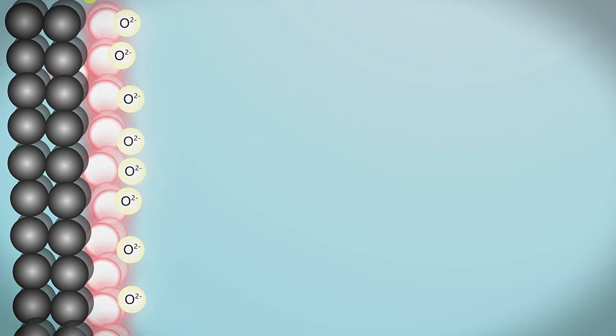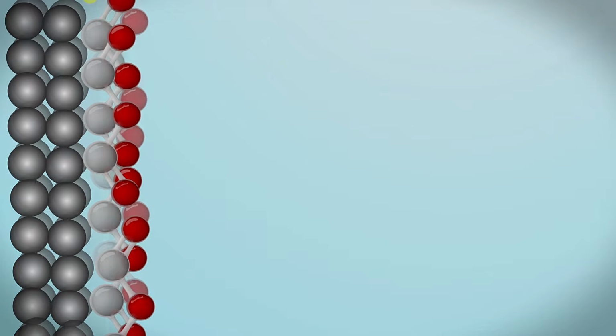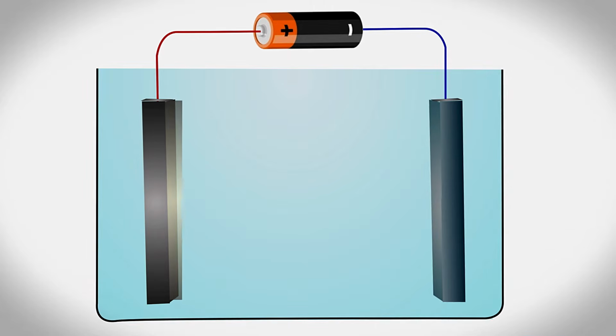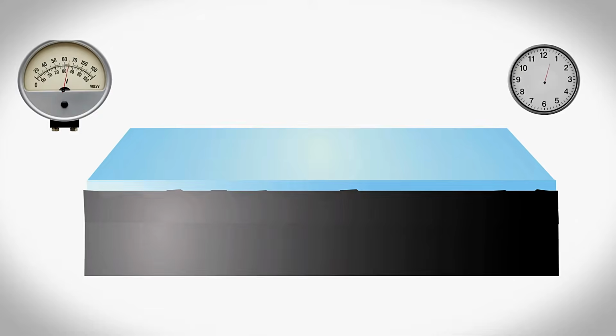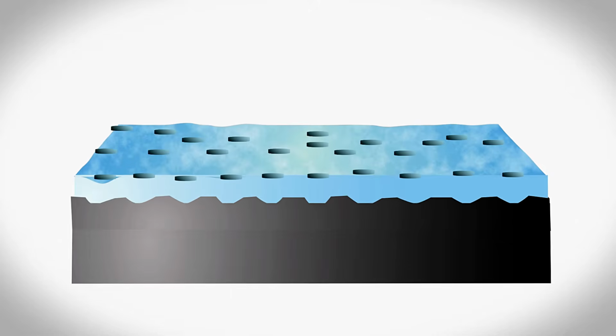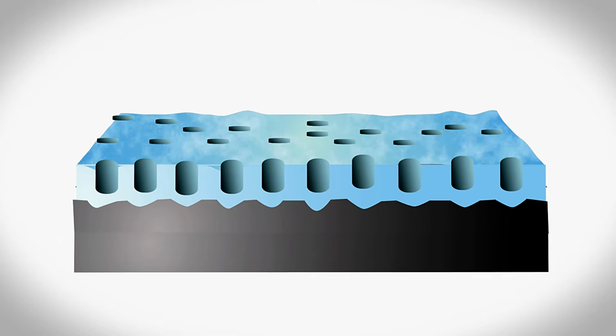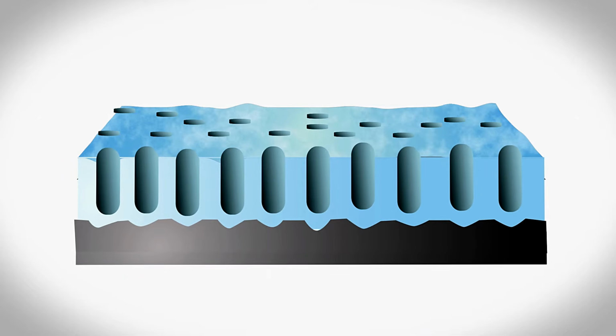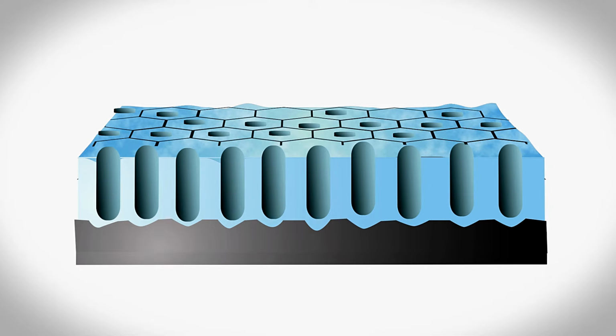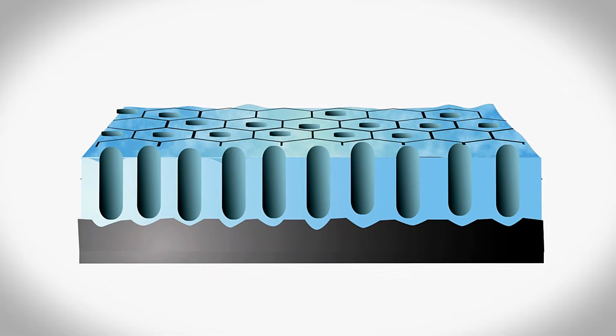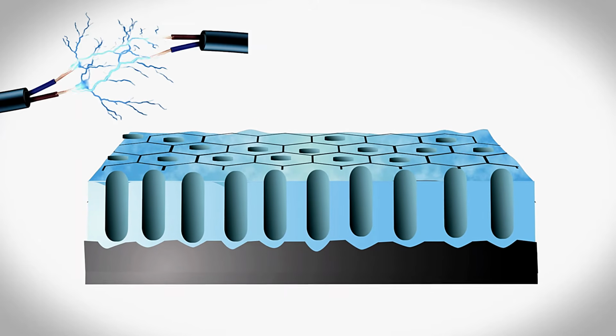Under the huge electric field, they meet to form Al2O3, a dense, glass-hard oxide that literally grows out of the metal itself, not on top of it. First, a thin barrier layer forms, a compact dielectric only tens of nanometers thick. As voltage and time increase, acid at the surface starts to dissolve the oxide, while the field keeps pushing new oxide from below. The fight between build and dissolve spontaneously organizes into millions of vertical nanopores. Under the right conditions, those pores self-arrange into a near-perfect honeycomb. You've just turned boring metal into a precision nano-engineered material using nothing more than electricity and acid.